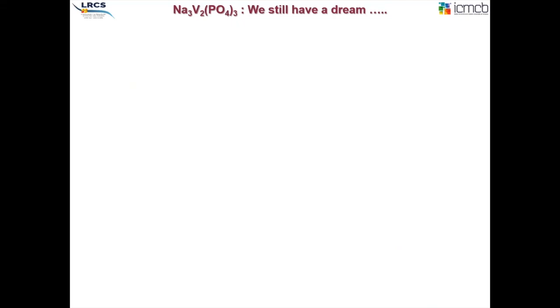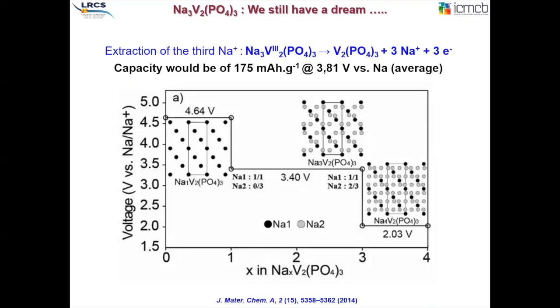Many people, I think, have been trying to get further in NVP and to try to fully extract the third sodium. You know, I was just talking about from Na3 to Na1 here. That gives an operating voltage of 3.4, but the capacity is still limited to around 110, 120 milliampere hours per gram. The ideal case would be to be able to reversibly extract the third sodium towards V2(PO4)3,